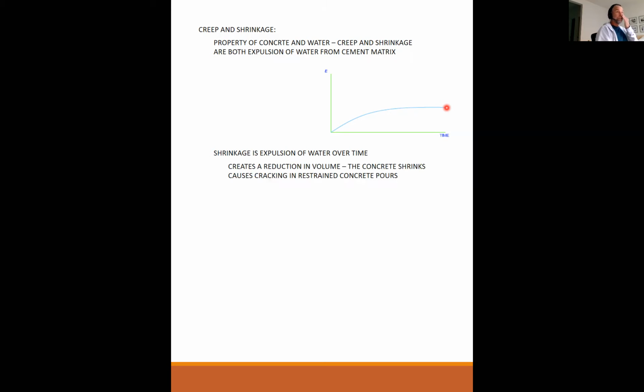And it creates a reduction in volume. The concrete will shrink because you're losing a volume of water to the atmosphere. So the concrete itself actually will shrink. And most concrete is restrained in some way. So as it's trying to shrink itself, something is going to try to restrain it from shrinking, and it's going to crack. So I'll just say it right up front, so nobody's surprised: all concrete cracks. All concrete structures crack. Cracks are not evil. They're not the end of the world. All concrete will crack. What we do in our jobs is we control the cracking, okay?